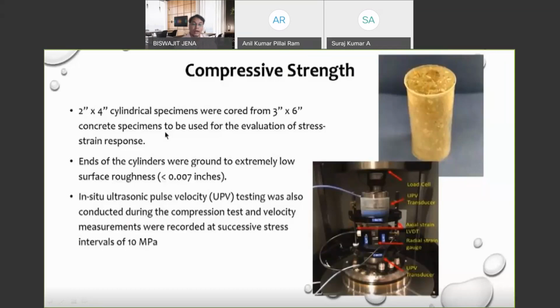If you have to do that, and we are doing this in a displacement control mode, in a closed loop testing with a radial strain control, because your radial strain is much more, and the overall volumetric strain is axial strain plus twice the radial strain. So your radial strain is very sensitive, and therefore you have to control the radial strain after you have loaded to about 50% of the peak. So there are a couple of different load changes that you have to do in this kind of testing, and we did ultrasonic pulse velocity testing as the specimen is being loaded, so that we can non-destructively measure the elastic modulus under different loading stages.